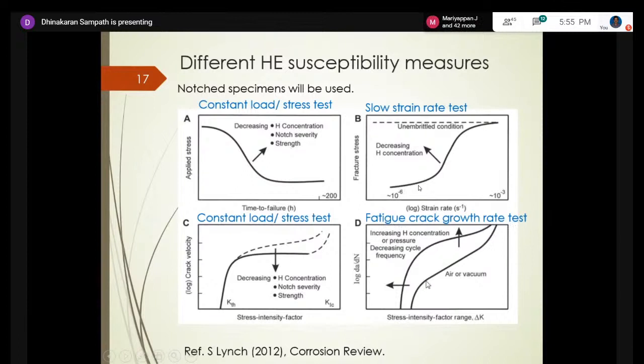Fatigue crack growth rate test. Again, this is crack growth rate as a function of stress intensity factor range. It's a range because it's the difference between the max and min of the sinusoidal wave. This is the crack growth rate, the typical sigmoidal curve. In the presence of hydrogen, it goes up several orders of magnitude. The crack growth rate increases throughout the entire regime, including the threshold and the Paris region.